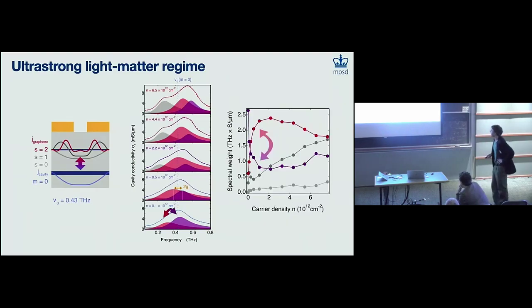Another interesting feature is that we see a spectral weight transfer. Here, at the lowest carrier density, this purple Lorentzian is mostly the cavity mode character. Then you can clearly see as we start to gate the carrier density, we are taking spectral weight out of this mode and putting it into the pinkish mode here. And so here's the graph where you can really see these two modes are exchanging their spectral weight.